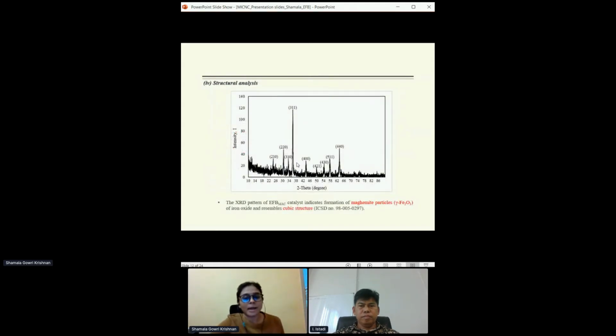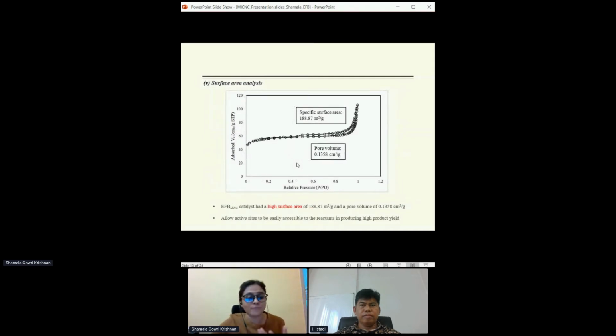And the determination of magnetic compound in the catalyst was confirmed by XRD analysis, where it shows that the catalyst has maghemite particles of iron oxide with cubic structure. The catalyst also had a very high surface area of 188.87 meters squared per gram with a pore volume of 0.1358 centimeter cubed per gram, which indicates that the active sites can be easily accessible to the reactant for a reaction to occur.